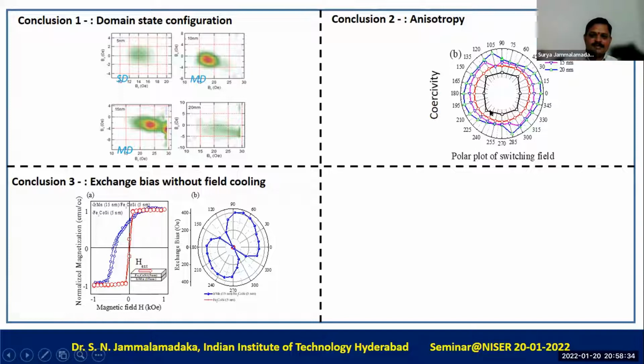If isotropic, the plot means you must get a circular kind of fashion. I understand. But if you look at for 5 nanometers, you do see a very clear four-fold anisotropy. Yeah, you are making the polar plot. Actually, if you make a simple XY plot, then you will see the peaks will not be very significant. That is, between the peak and the normal level, it is not a big difference. So it is not very anisotropic. But however, if you look at the FFT of MFM image, we do see very clear four-fold anisotropy. I don't know if the FFT of MFM is a good idea to actually quantify the anisotropy. But at least we get some idea about what kind of anisotropy.